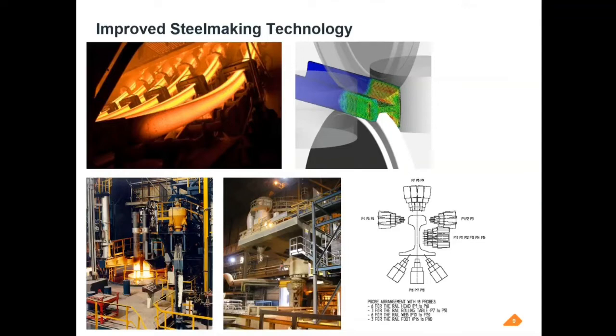So ingot casting introduced a lot of problems. You would have pipe defects in the ingots. You would have a lot of inclusions. You would have a top and a bottom of the ingot with different levels of performance, from one end of the rail to the other. When they introduced continuous cast bloom manufactured rail steels, there was a step change improvement in the number of rail breaks from internal defects and fatigue cracks from internal stress raisers, non-metallic inclusions, pipe, for example, and porosity.